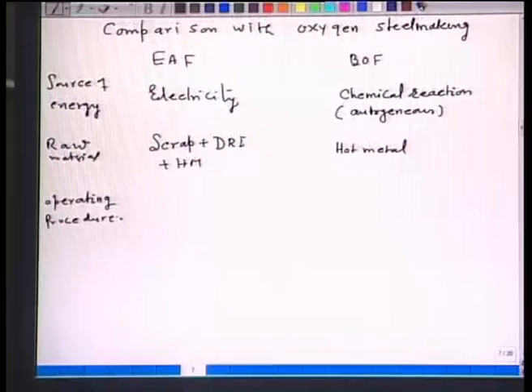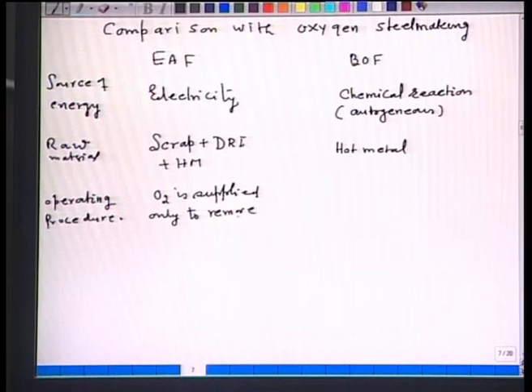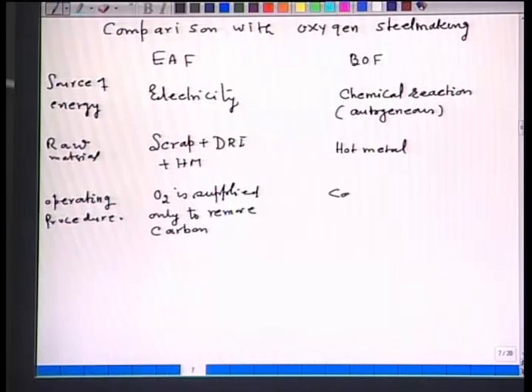is hot metal. In the operating procedure, in electric arc furnace, oxygen is supplied only to remove carbon. During meltdown stage, sometimes you do require oxygen supply, but essentially you require oxygen in case of electric arc furnace when you require to remove the carbon. Whereas in basic oxygen furnace, continuous supply of oxygen is to be carried out.